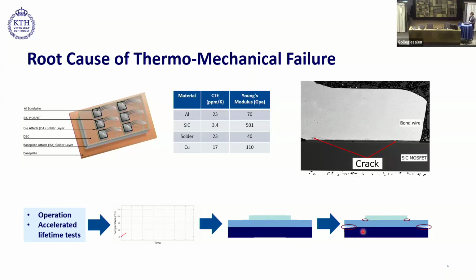Here is one picture of the device that we failed at KTH. It might not be clearly visible, but there is a crack at the interface of the bond wire on both sides. Therefore, this device failed at the end of the test due to bond wire liftoff.